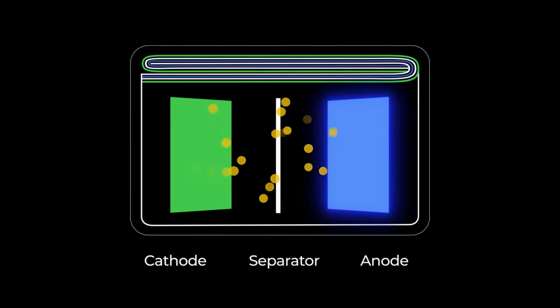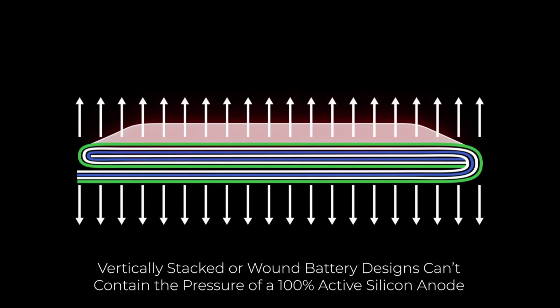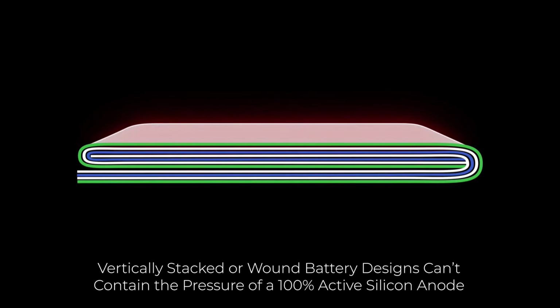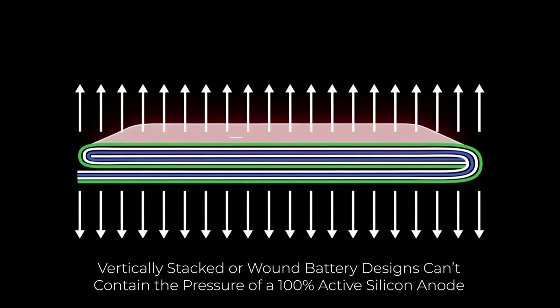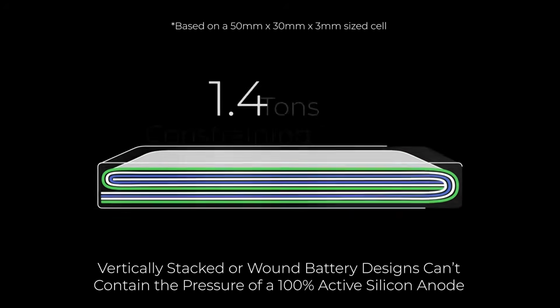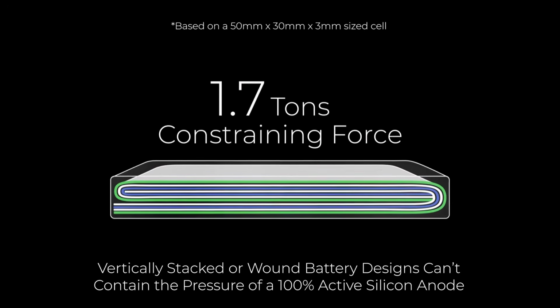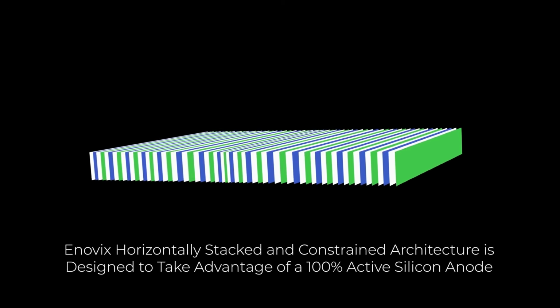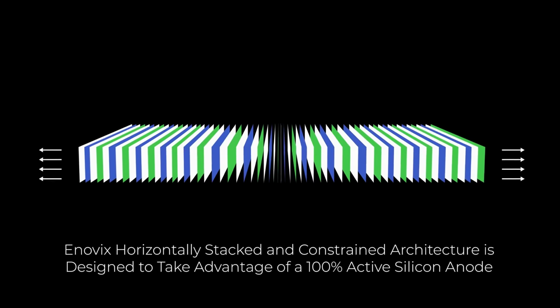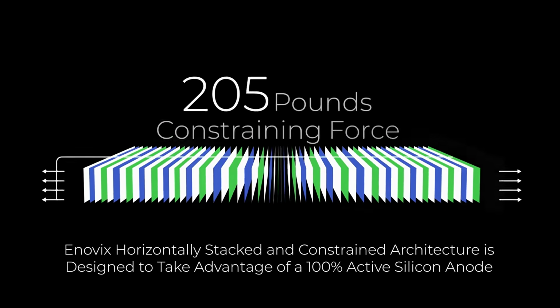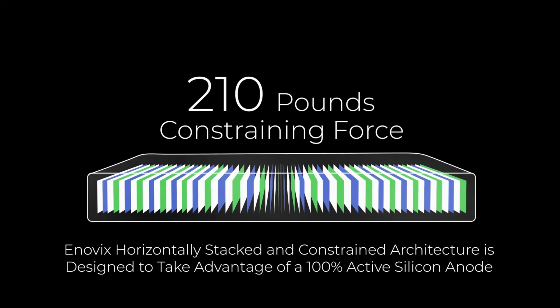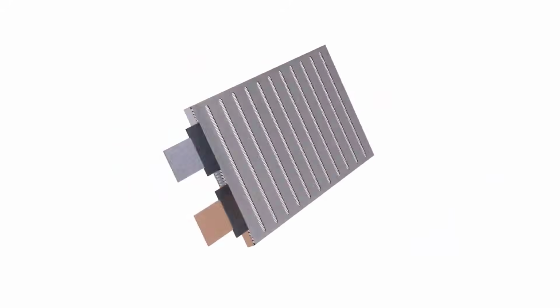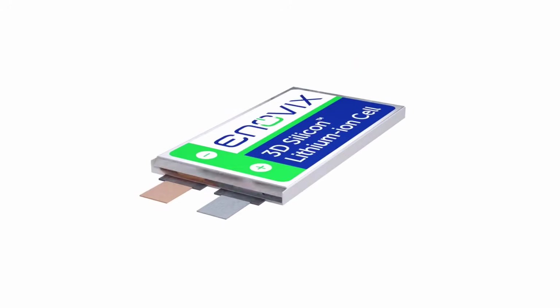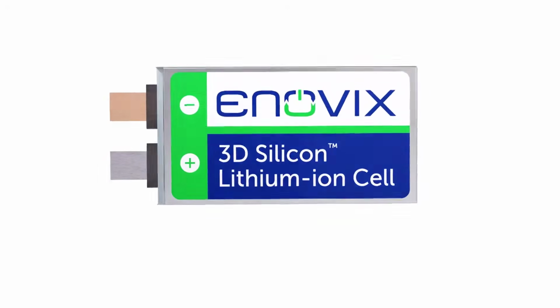During initial charging, silicon can more than double in thickness, generating pressures of up to 1,500 psi. In conventional cells, this force acts on a large surface area, creating destructive loads. Enovix's design redirects this pressure to much smaller faces, reducing force from roughly 1.7 tons to about 210 pounds in a phone-sized battery. A 50-micron stainless steel constraint system further limits swelling and keeps materials under constant compression.